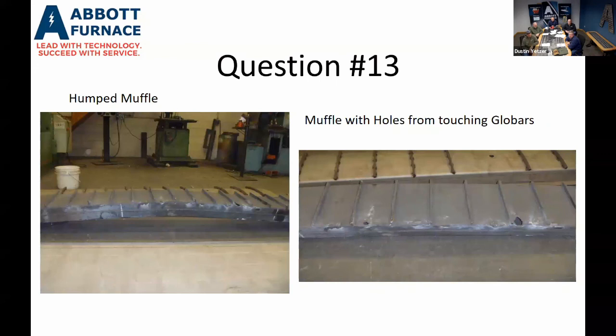So we have a procedure written up that I'd feel free to share if anybody's interested. So we put our new muffle in, our furnace is cold. We're going to bring that furnace up to 400 degrees. We always ramp at 100 degrees an hour Fahrenheit. And that, as Donnie talked about, with the Globars, the electrical components, everything, is going to give us a nice even heat rate. We're not working things too hard to bring it up at that speed. So we're going to bring it up 100 degrees an hour, get to 400, stop for 2 hours, and then do our next step.